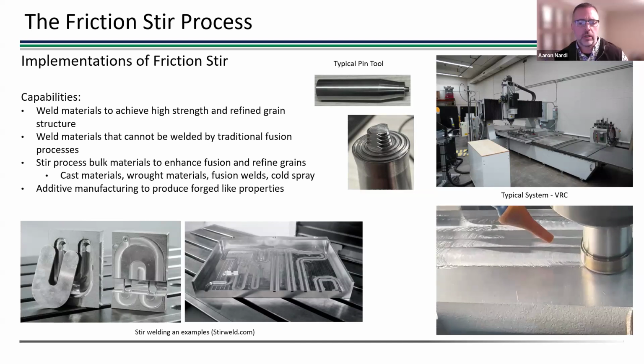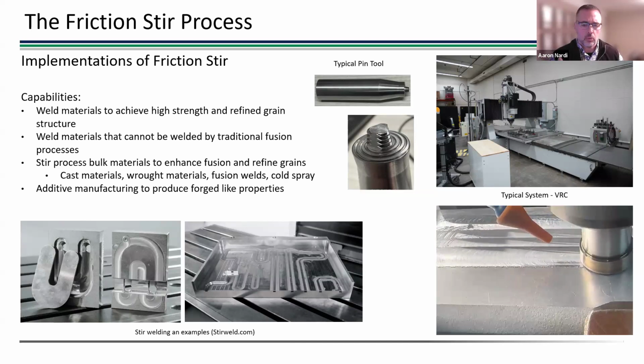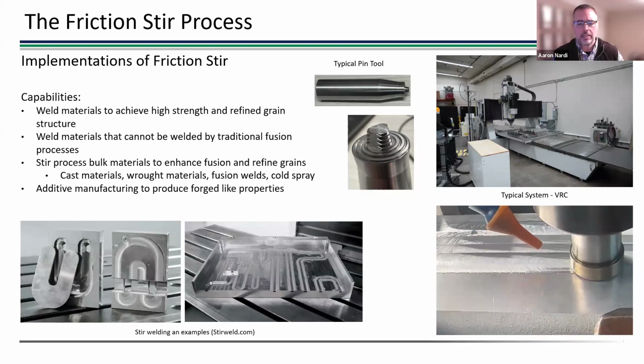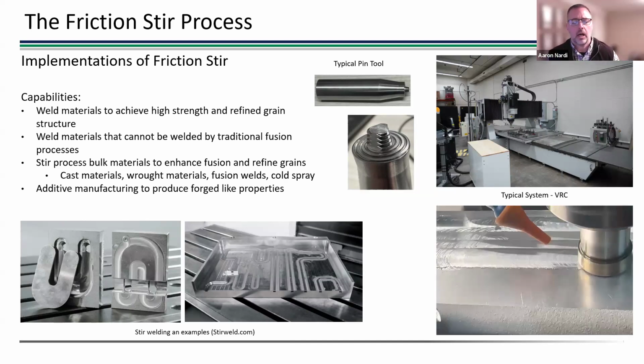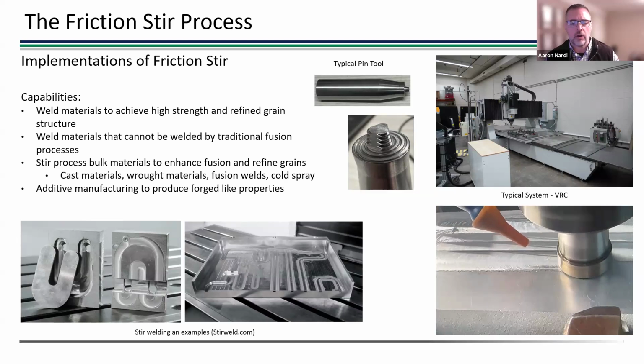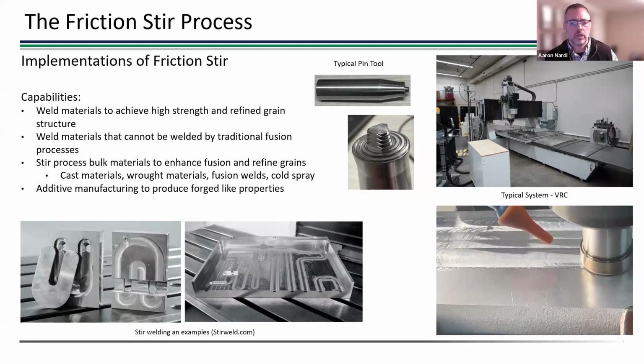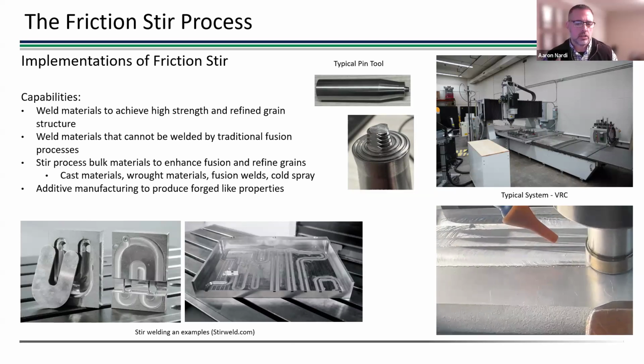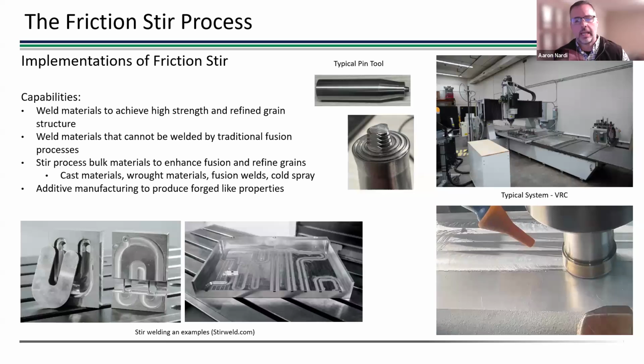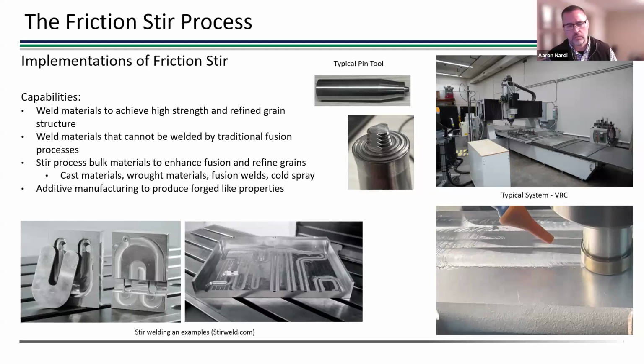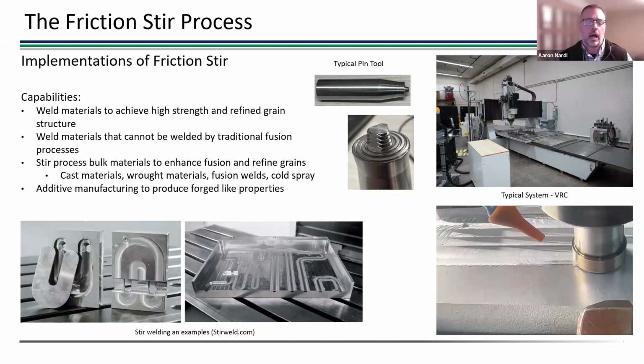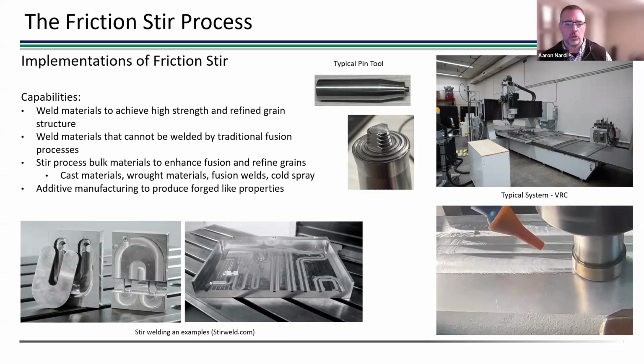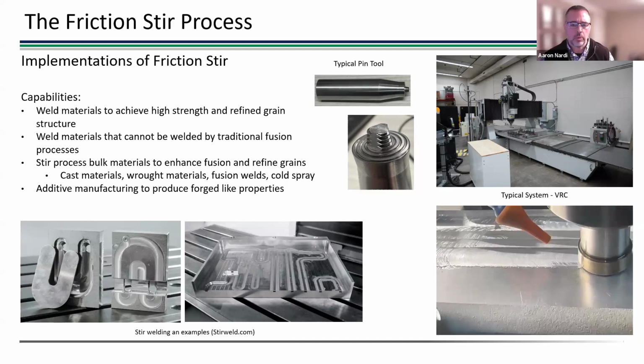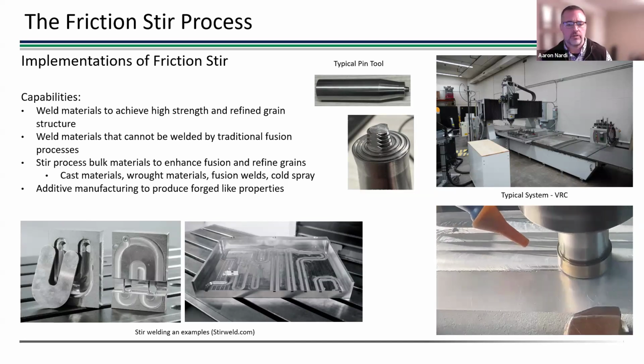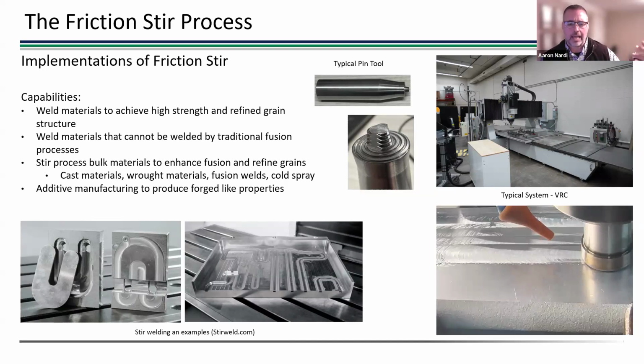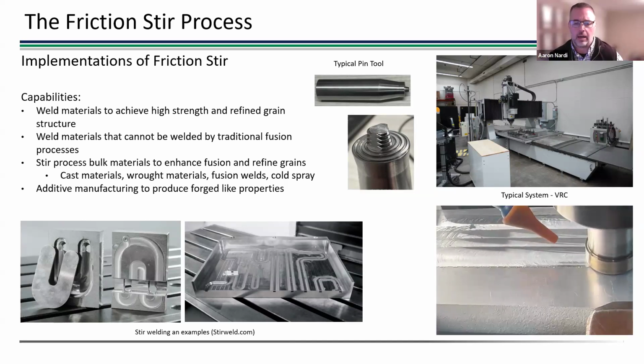Now the friction stir welder, we have a couple of them now. One of the ones you see in the image up at the top is what's being operated in the little video here. That system has a very large footprint, so you can do large parts, but it has a certain load capacity. The second machine we have is a 5-axis machine. So this is 3-axis, and we have a 5-axis machine as well. So you can do much more complicated parts and much higher loads. This machine can do 1/4 inch, 1/2 inch of aluminum without too much difficulty. When you get much past that, you switch over to the higher load machine to do that work.